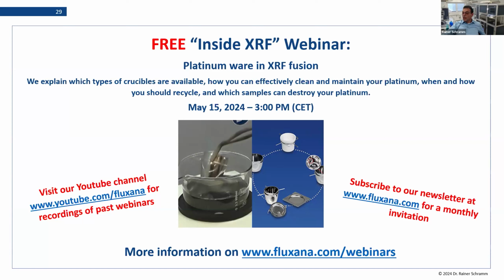So another question, how can I improve to avoid the formation of bubbles when I prepare fused beads of limestone? These samples are not calcined previously. That's a very good question because indeed, if there are volatile parts like carbon dioxide in your material and you heat that up, you form a lot of bubbles. And yeah, what can you do? The best is that you fuse longer in the hope that you fuse so long that everything is out, or you have to calcine first.